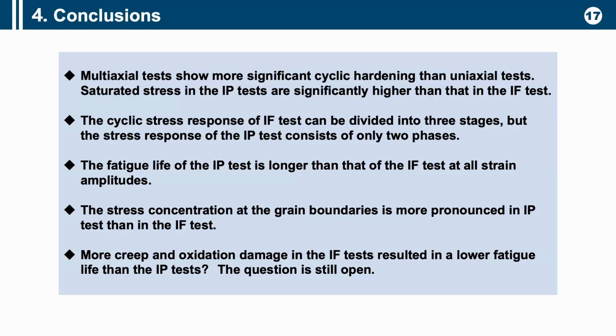The fatigue life of the IP test is longer than that of the IF test at all strain amplitudes. The stress concentration at the grain boundary is more pronounced in the IP test than in the IF test. And last, we get more creep and oxidation damage in the IF test, resulting in the lower fatigue life than the IP test. But we didn't find more evidence. So the question is still open.